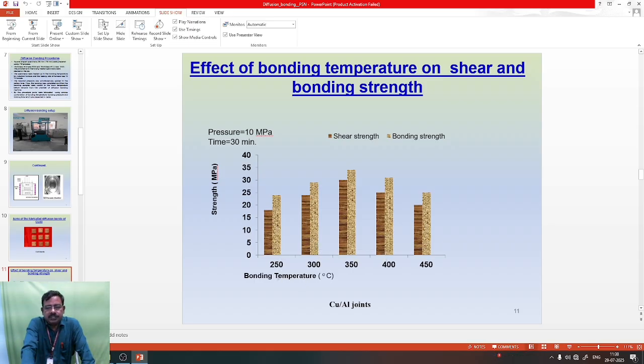Initially at the 250 degrees Celsius, the shear strength and bonding strength are very less. When the temperature increases, the bonding strength and the shear strength increase. When the temperature increases up to 350 degrees Celsius, the shear strength and bonding strength are increased. After the temperature of 350 degrees Celsius, the shear strength and bonding strength are reducing. And again at the 450 degrees Celsius, these two strengths are again reduced because 350 degrees Celsius is the optimum temperature. At this temperature, the diffusion layer thickness is optimum.